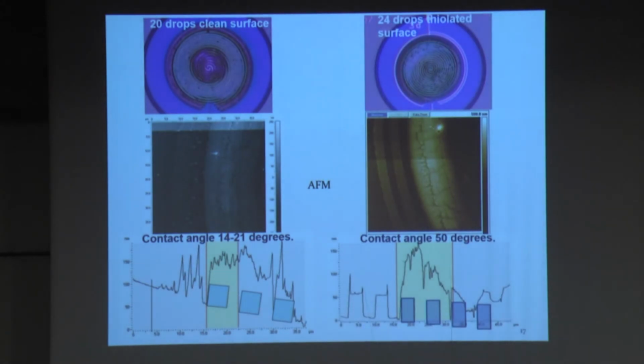Now, if you treat your surface before inkjetting, you can increase your contact angle, so the same volume or even bigger makes a smaller splat. Again, you can see very nicely the coffee ring effect. Please notice that the coffee rings have some pinholes along the perimeter of the electrode themselves.